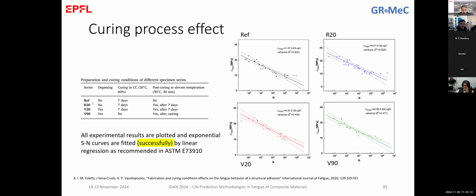The reference specimens, business as usual: no degassing of the specimen, 7 days in the lab, and then no post-curing. Then we had this R20 series specimens where, again, we didn't do any degassing. So we mixed the specimen and we let the air in the specimen. 7 days curing in the lab. And then we had the post-curing at 90 degrees for 30 minutes after these 7 days.